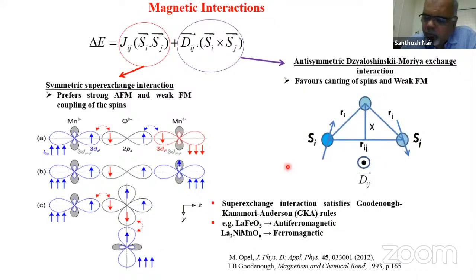Predominantly the exchange interactions which decide the magnetic properties in these systems are called superexchange interactions. For example, if you have two manganese ions talking to each other through an oxygen ion, it forms a semi-covalent bond where the electrons are shared in the bond. There are certain rules, the Goodenough-Kanamori-Anderson rules, which tell you whether something is ferromagnetic or antiferromagnetic. Antiferromagnetism is predominant, but there are enough examples in the literature where you can have weak ferromagnetism also. I'm not going to talk about the DM interaction, which is not very important.